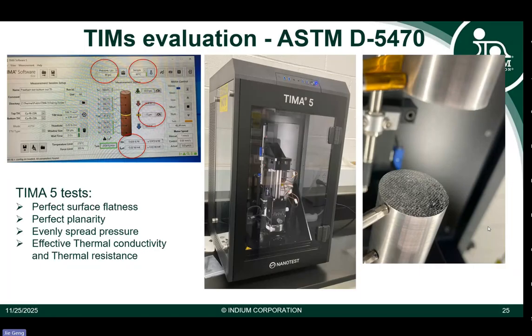So for the TIM materials, the two most important things are effective conductivity and the thermal resistance. So this kind of testing is all based on ASTM D5470 standard. And the typical equipment available, here shows the example, the Nanotest TIMA 5. So in this machine, you can easily change the pressure, temperature, and the bond line thickness. So you can get the thermal conductivity and thermal resistance from different conditions.